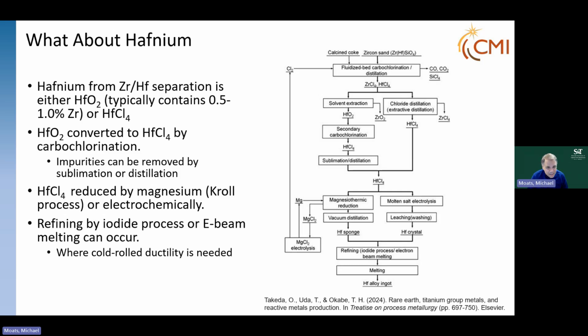The hafnium that comes out of either extractive distillation or solvent extraction, and then secondary carbochlorination, I end up with a hafnium tetrachloride. We can go through the Kroll process and make hafnium sponge like I just said. You can also go through molten salt electrolysis, and this is actually practiced in France. So I'm going to talk a little bit about molten salt